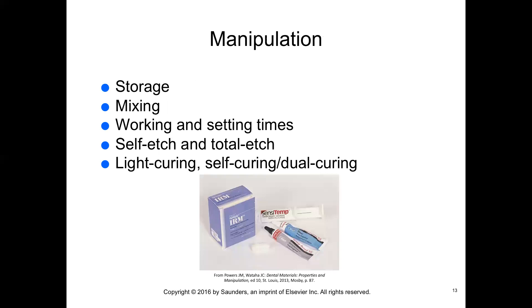Cements should not be stored in warm or humid areas of the dental office and can be stored in the refrigerator. It is important that cements be mixed to their appropriate consistency in accordance with manufacturer's recommendations with meticulous attention to detail. Cements that are mishandled may lead to difficulties in seating or retaining the restoration and may promote pulp sensitivity. Cements may be hand mixed or may come in pre-dosed capsules and syringes, and the working time and setting time are considerations in the choice of cement and mixing mechanism.